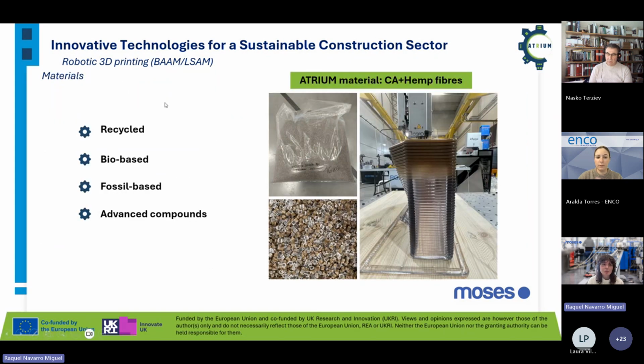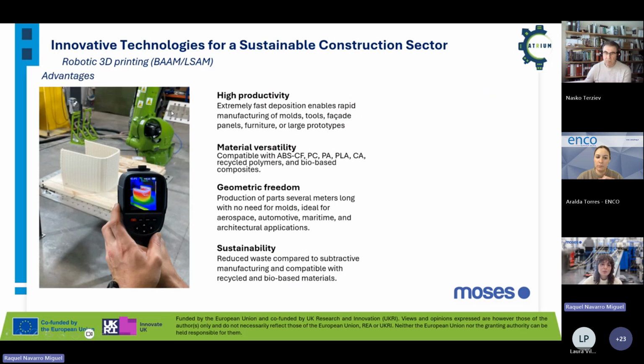So we can print different kinds of materials: recycled, bio-based, fossil-based, and also advanced compounds. In this case, I'm showing you the material that we use in the ATRIUM project. This is cellulose acetate with hemp fibers. Okay, this is a material that we obtain through extrusion compounding, and also you can see here the degradation between the virgin material and the compounded material. So we made some trials just to check the right parameters of the 3D printing process.